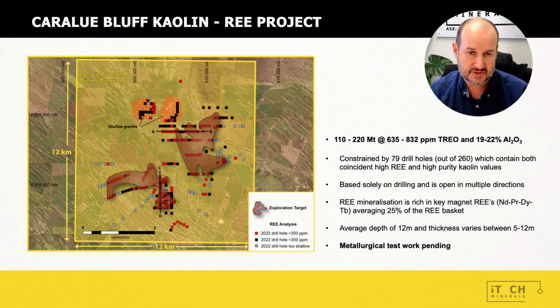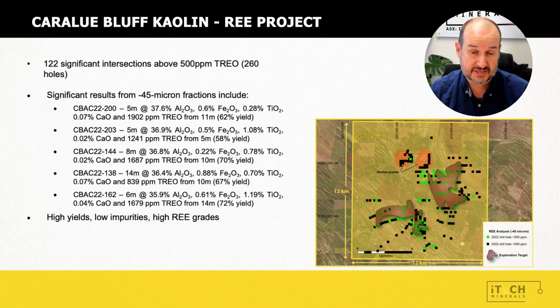Now, the rare earths within this mineralisation are very much enriched in the key magnet rare earths. So that's neodymium, praseodymium, dysprosium and terbium. And they make up about 25% of the rare earth element basket. So that makes it a high value rare earth element basket. What we did notice is when we upgraded this material to extract the kaolin component of the mineralisation, it also upgraded the rare earth component significantly. And on average, it upgraded it by 176%.